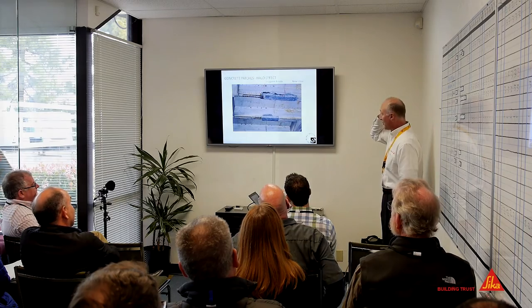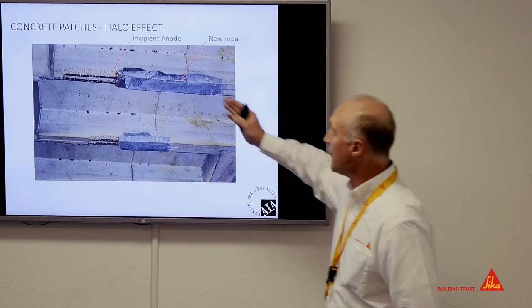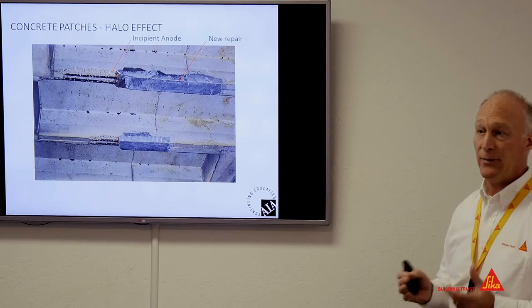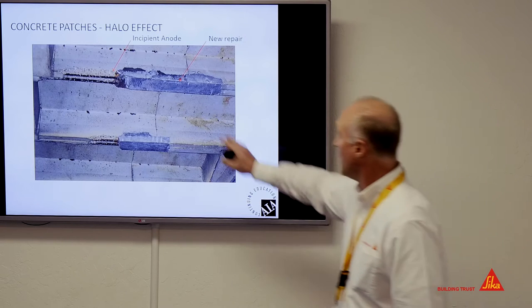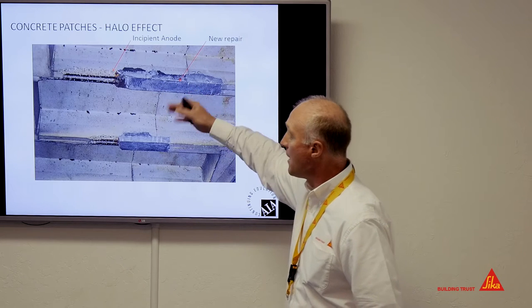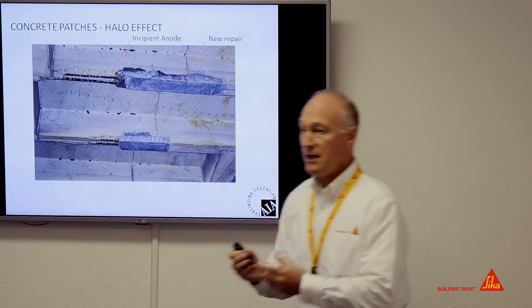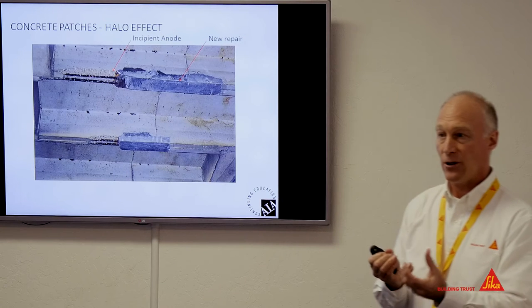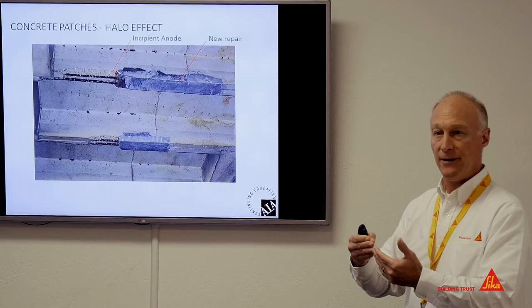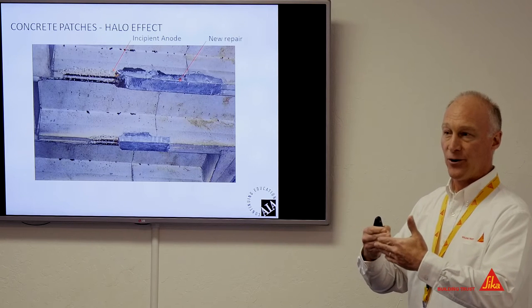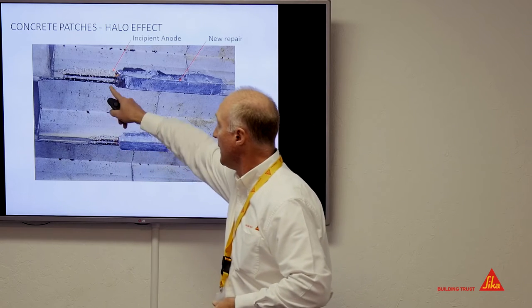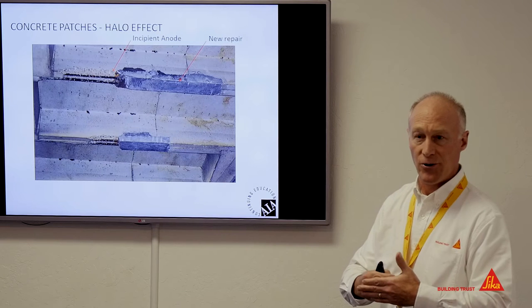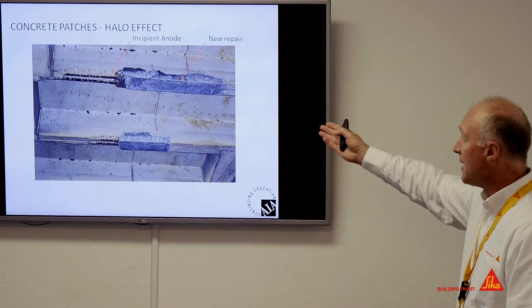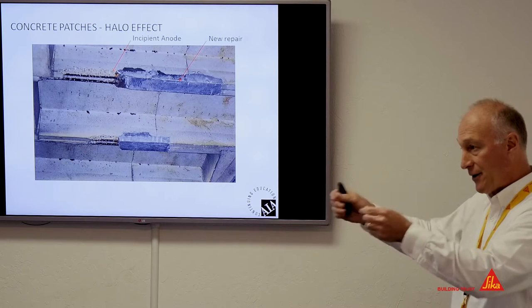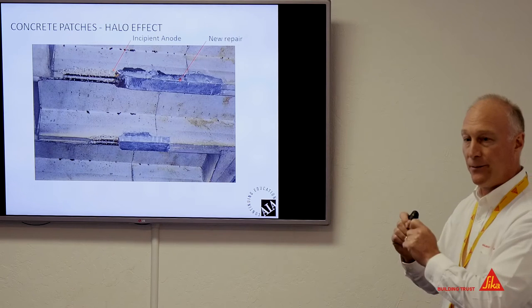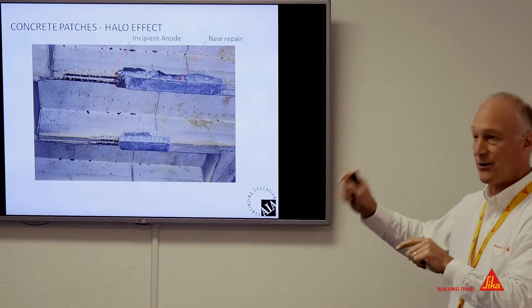Here's an example, I referred to it earlier, but this was an area that had been repaired, and we call this the ring halo effect, or the incipient anode. When I've placed this mortar or concrete around the steel, this reinforcing steel is actually in two different environments now. It's in a possibly chloride contaminated environment, and then it's in a fresh concrete environment. The difference in those environments will actually cause a corrosion cell. And it will cause the steel that's adjacent to that patch to accelerate in corrosion, which then can lead to a spall. So here, the contractor did everything right. They sounded the area out, they excavated where the problem was, they put the repair in, but there's nothing to really address outside the patch.